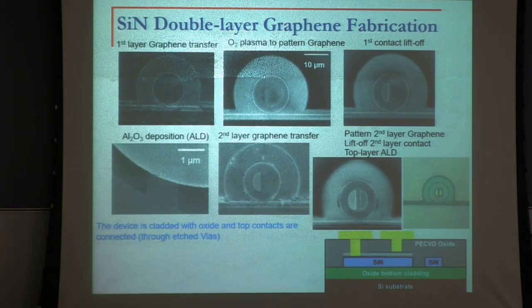This is double-layer graphene on silicon nitride, similar to silicon nitride, silicon. The reason we use graphene is because, on paper at least, graphene should have very low resistance. Now, the speed is limited by R, resistance, and C, capacitance of this device. By reducing the resistance, we should get 100 gigabit per second on paper.